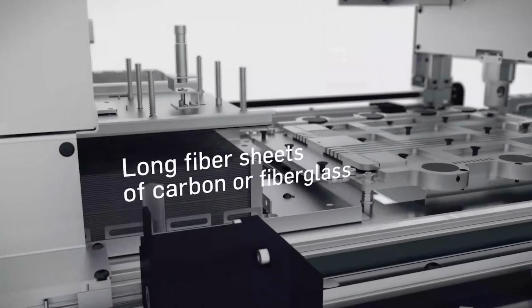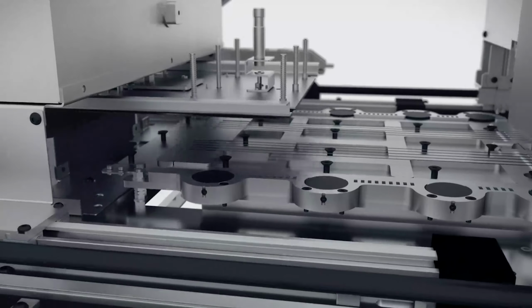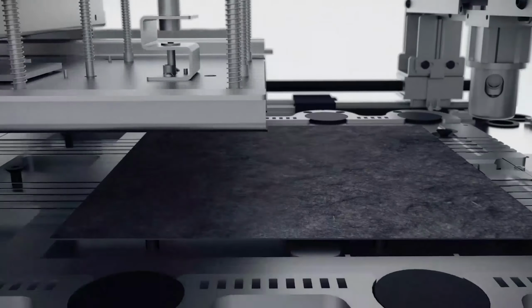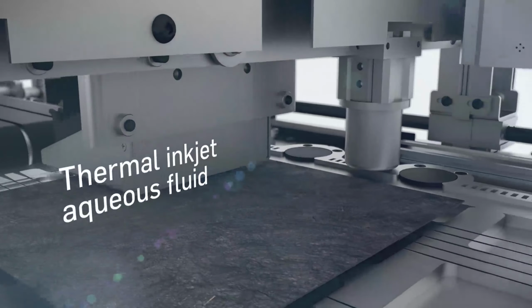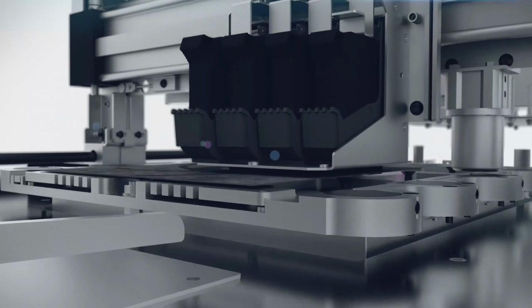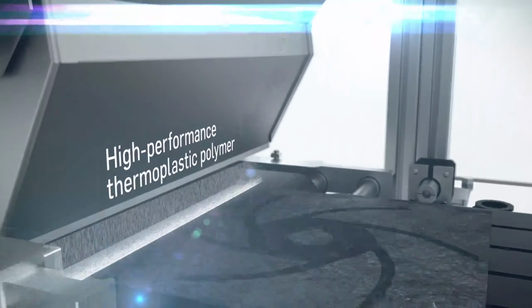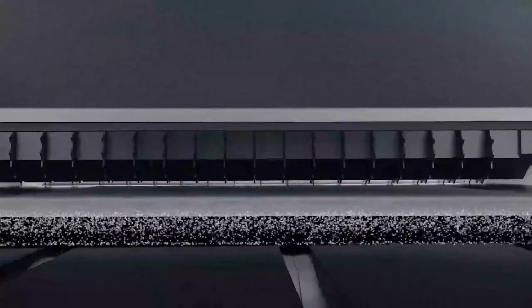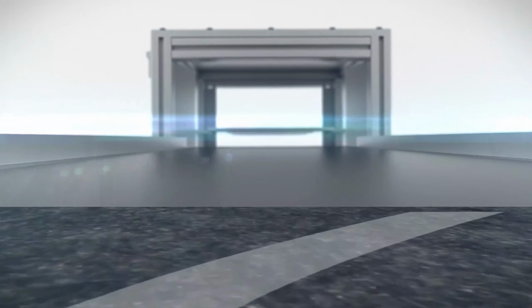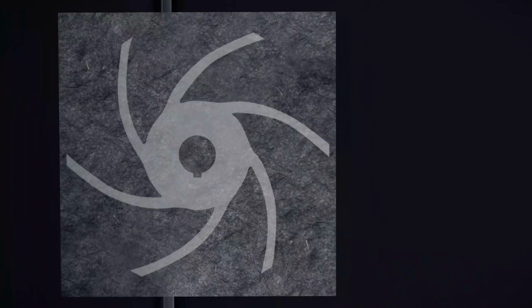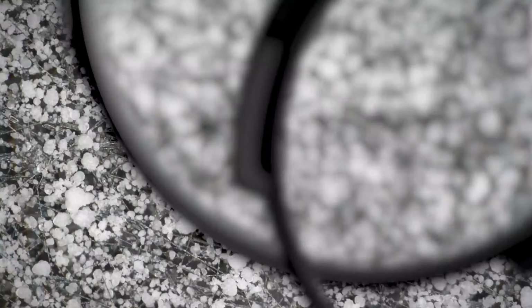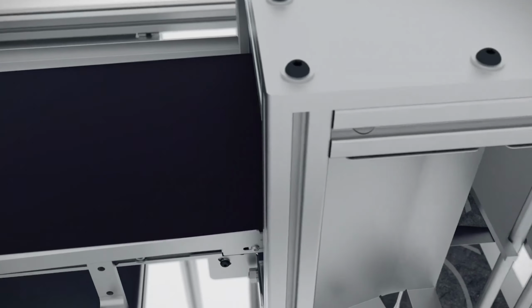The machine starts with a stack of sheets. The images of the layers are printed with an aqueous fluid onto fiber sheets. The sheets pass through a powdering system where polymer powder is flooded onto the sheet. The powder sticks to the sheet where the fluid is deposited. The excess powder is vacuumed off and the polymer is selectively deposited on the sheet. Microscopically, you can see polymer particles penetrating the sheet. The process is repeated for all of the layers of the part. The sheets are then stacked to complete the entire printed geometry.